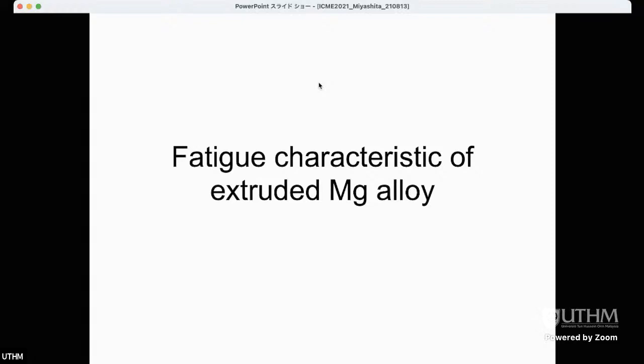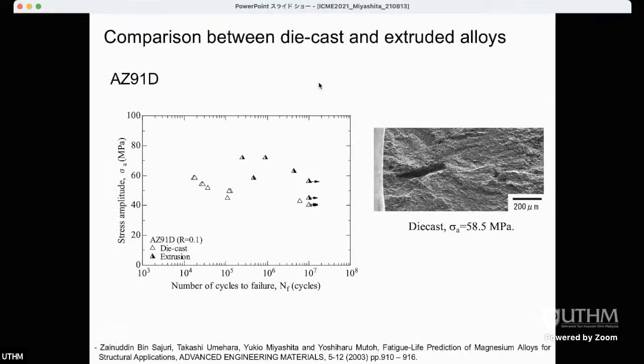This is a very fundamental and basic property of extruded alloy. As I said in the introduction, in most cases magnesium products are produced by die cast. This figure shows the results of the fatigue strength test, comparing the die cast one and the extruded one. In this case, we carried out the fatigue strength test on AZ91 magnesium alloy, which includes 9% aluminum and 1% zinc. As you can see from this figure, die cast material shows lower fatigue strength compared to the extruded one. According to fracture surface observation of die cast material, in some cases we can recognize this kind of cast defect as a fracture origin.